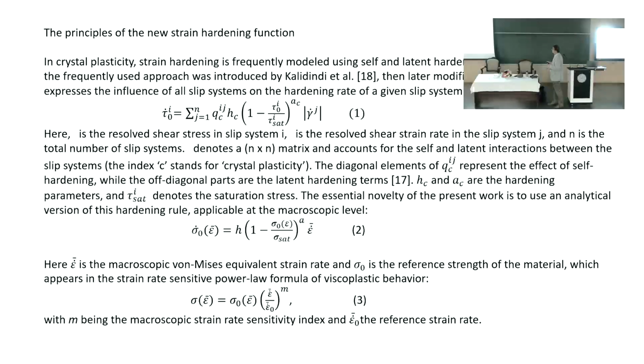With these 3 parameters together, one can control and increase the strength of dislocation slip, and this process is able to produce in polycrystal plasticity a really very nice agreement with experiment. So now the idea came from here — this is a simple rate equation introduced 30 years ago.